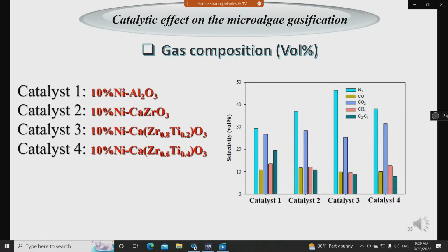Also, the presence of zirconia in catalyst structure increases the thermal stability, which can lead to reduced sintering and increase the nickel dispersion. With the addition of titanium into support structure, oxygen vacancy defect can be created in the perovskite structure, which increases the oxygen mobility of the catalyst. This is the main reason of the high activity of the catalyst 3.